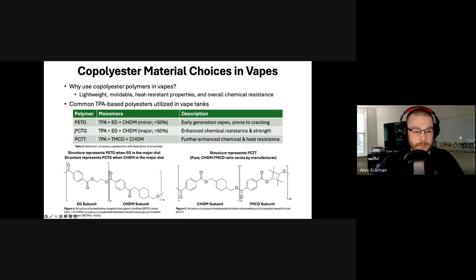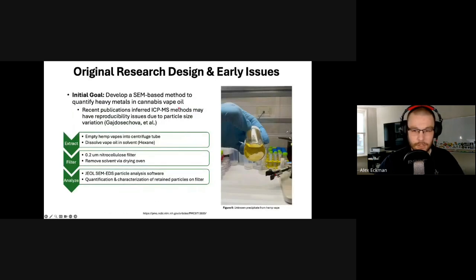And so recently, the industry switched to this PCTT, and we can see the structure here on the bottom right. The thought was that having a blockier ring structure in here is going to change how the polymer chains stack on top of each other. And that's going to alter different things like the crystalline versus amorphous properties, different chemical and heat resistance properties. And so this was probably back in 2023, from what I found, the industry switched to this PCTT polymer. And as we are about to find out, it potentially may not be the perfect polymer to use.